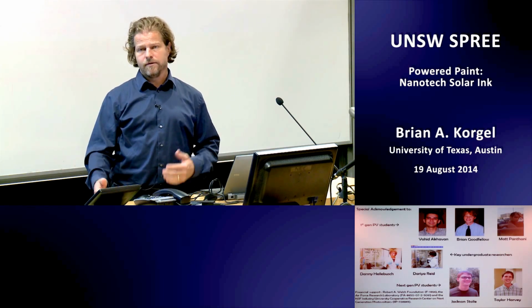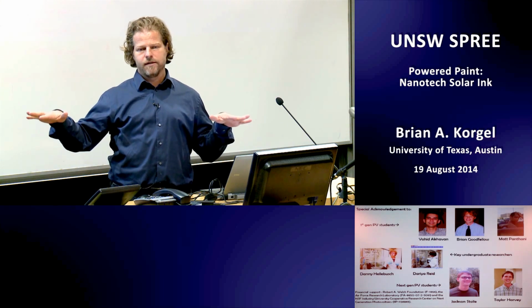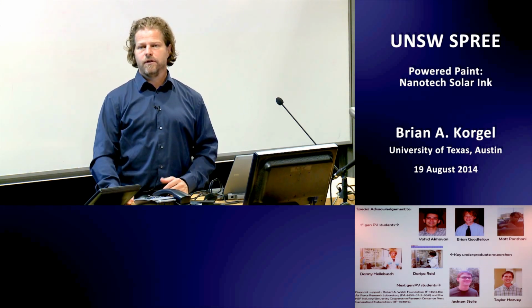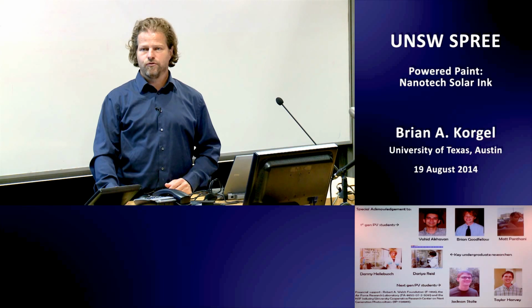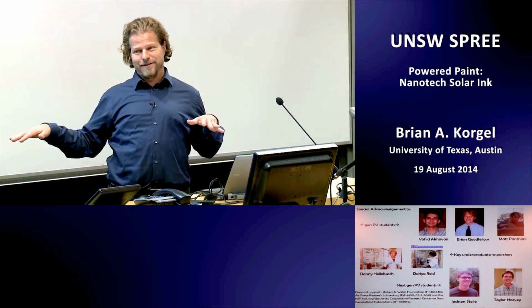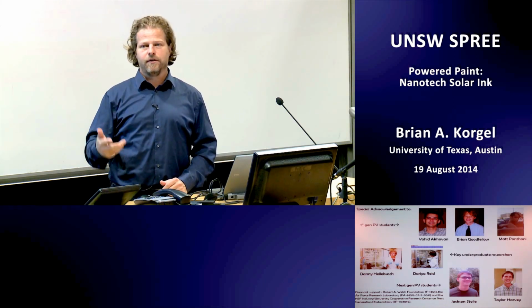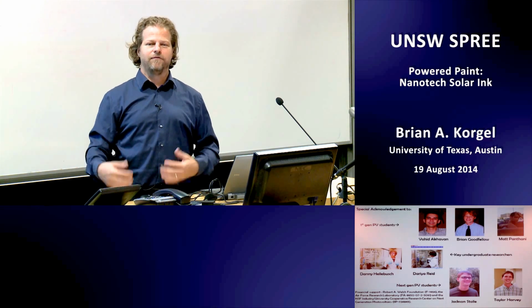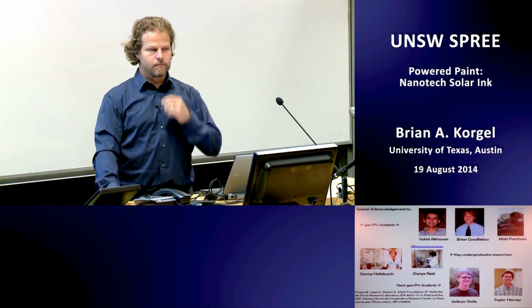So cadmium telluride has taken off, and First Solar can make really inexpensive devices. If you compare the two processes, CIGS and cadmium telluride, you're subliming cadmium telluride onto a substrate at 400 C under vacuum, but not ultra high vacuum, and that's a pretty easy process to control compared to the selenization. So I would love to figure out a way to get rid of selenization and sintering. But the problem is, if we get rid of it, we make 3% devices, and with selenization you can make 14%. So everyone is lured towards selenization because it feels better to make 14% devices than 3%, but it's not solving the problem.